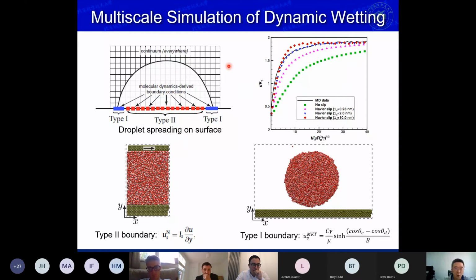Specifically, we use VOF to simulate the whole droplet spreading, but at the boundary, we use two types of boundary conditions, and in the center of the solid liquid interface, we use the Navier slip. It's a standard slip model. But if we only use this model, there is just one parameter called slip length. We can compare the VOF results to the NEMD results as shown in this figure. The black line is the NEMD data, the full NEMD simulations. And if we use VOF without any slip model, as you can see, the spreading is much slower than NEMD. If we use the Navier slip, we can adjust the slip length, the parameter.